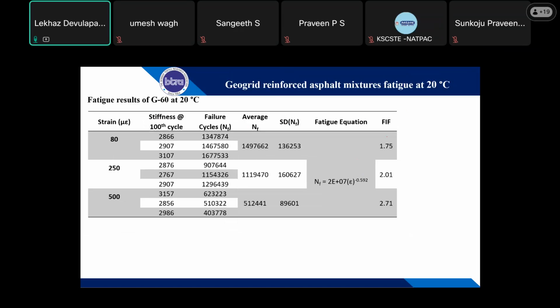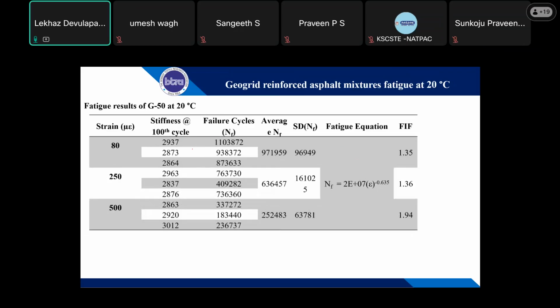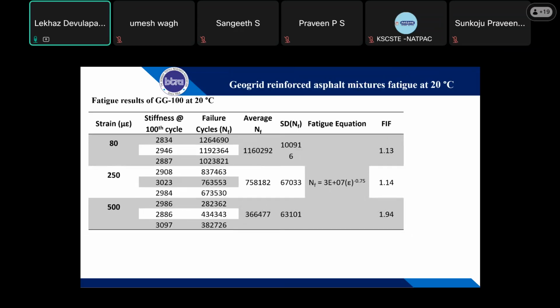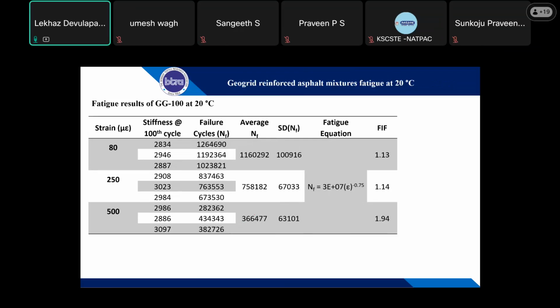And these are our fatigue improvement factors. You can see it was nearly 3 times improvement at 500 microstrains, nearly 3 times more than the control section. Even the polyester geogrid with backing has shown nearly 1.9, and this is also 1.9 for the glass grids, and for the glass grid with backing it is almost the same. We got high improvement, more than 1 time.